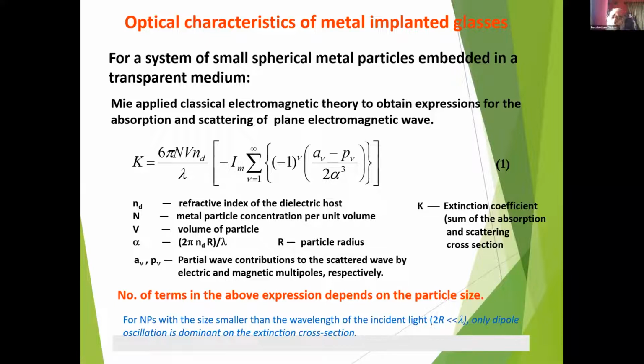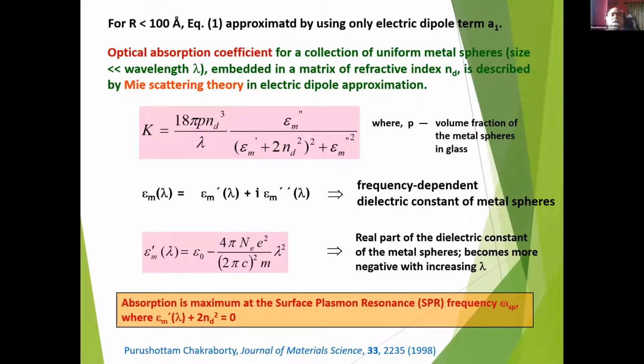Now, when the size of the particle is very, very small, maximum 100 angstroms, that is 10 nanometers, then we have seen that the monopole, the magnetic multipoles and electric multipoles can be ignored, and then you get a very simplistic expression for the extinction coefficient.